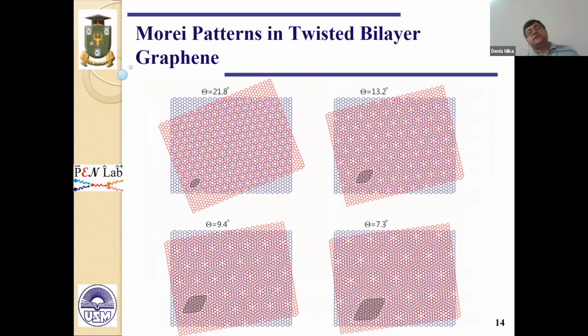And in the last part of my talk, I would like to discuss thermal properties of twisted bilayer graphene. When two graphene layers are placed on top of each other, they can form a moiré pattern. In this case, one layer is rotated relative to another layer by an arbitrary angle. There are two different moiré patterns, commensurate and non-commensurate. In the case of commensurate patterns, the periodic crystal structure is retained, but the unit cell is larger than the graphene unit cell and depends on the rotational angle. In the case of non-commensurate patterns, there is no periodicity in the crystal structure. Generally, commensurate patterns look like flower tracery.